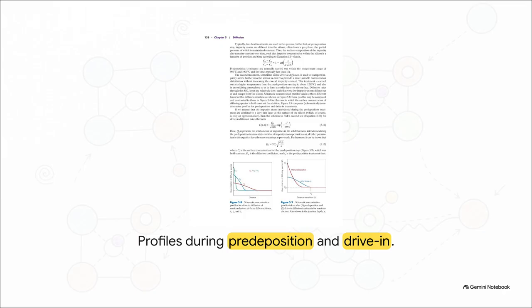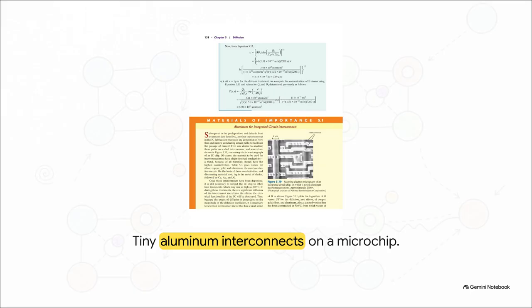Then comes the drive-in step. By applying high heat, using our Fick's second law cheat code to calculate the exact time, by the way, engineers meticulously push those impurity atoms much deeper into the silicon. This lowers the surface concentration, but spreads the atoms out to perfectly form the electronic pathways of the microchip. And the scale of this whole operation is absolutely breathtaking. We're talking about tiny aluminum interconnects on an integrated circuit chip that are maybe 4 micrometers across. To put that in perspective, that is a tiny fraction of the width of a single human hair. By using diffusion to embed impurities and then laying down these microscopic metallic roads, engineers can connect millions of electronic devices on a single chip.